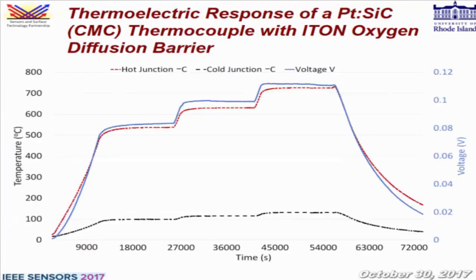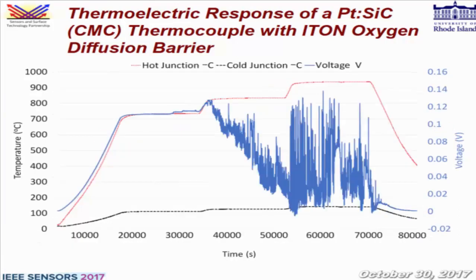We went ahead and tested that, and we had a pretty successful test. 500, 600, and 700 all worked well. So our next step was to see if this approach could survive even higher temperatures. It survived 700, and then we tried to go to 800, and it fails. The mechanism happening here is that there's no oxygen in this region, but now the platinum is reacting with the silicon carbide. So we had to figure out a way to prevent that from happening.